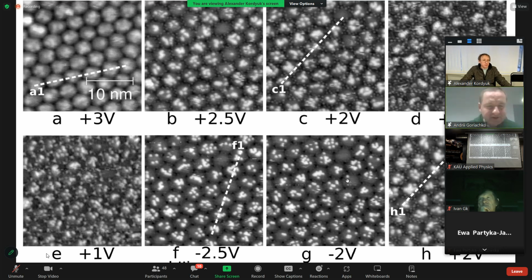So you can see the height corrugation. But at other energies of the tunneling electrons, some of them tunnel into the graphene because there are electronic states available for this. In other situations, for other energies, they tunnel right into the substrate because there are no electronic states, or the probability of tunneling is too low. These two phenomena give rise to all the other images, and it's easy to get lost here. However, maybe the uppermost and rightmost image, image D, explains the point.